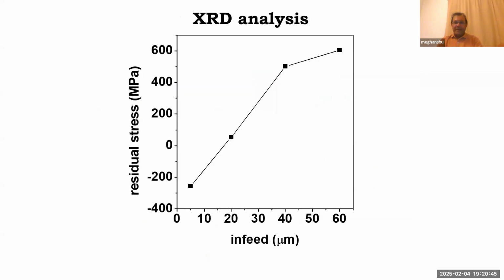So this is the actual experimental graph between the residual stress and a grinding operation. In this grinding operation, the downfeed or depth of cut was varied. When the downfeed was varied, it indicated that thermal damage was more. We came to know that in grinding, thermal damage is quite high because of negative rake angle, because of sparks, and because of low thermal conductivity of alumina and silicon carbide. That is why thermal damage increases with increase in depth of cut. You can see in this graph that the residual stress is increasing from minus 200, which means compressive, up to 600 megapascal. It is a very high amount, indicating very severe thermal damage in the ground component.